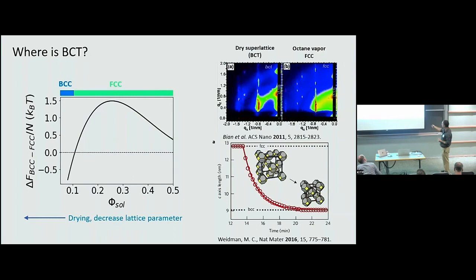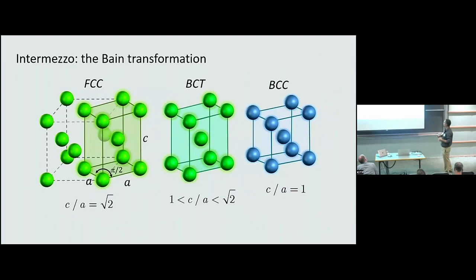Just to explain this a little bit better, the way you should think about it is, if you take the FCC cubic cell with four nanoparticles per cell, you can define another cell that has two nanoparticles per cell, the one in green here. That one is not cubic anymore, it's tetragonal, and it has a relationship between c and a of square root of 2.